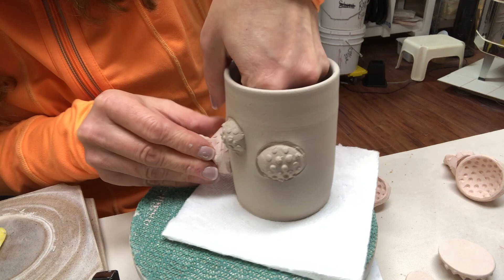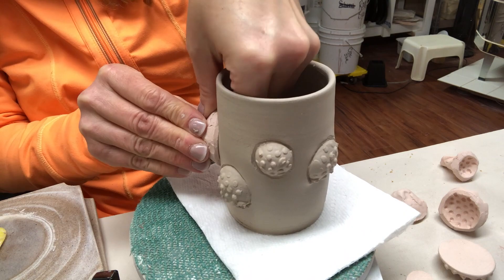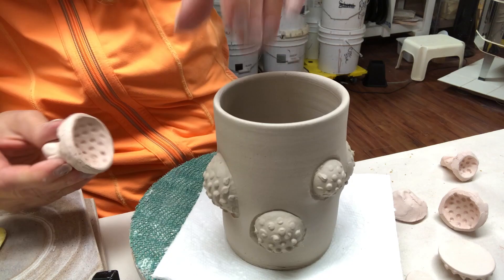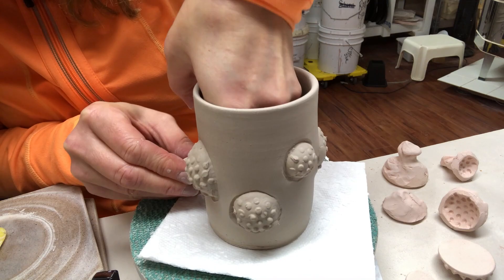You could use this with any sort of form — a shell mold, a basketball shape, all sorts of different shapes. You have to be careful not to press too hard right along the edge of the mold or you could crease it and create a hole. If you press too hard too quickly and make it bump out too fast, you could rip the clay if your clay wall is fairly thin.